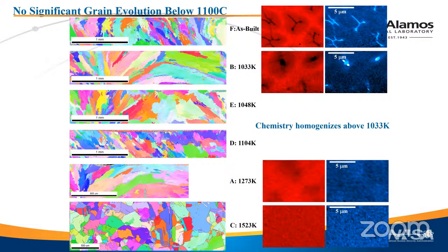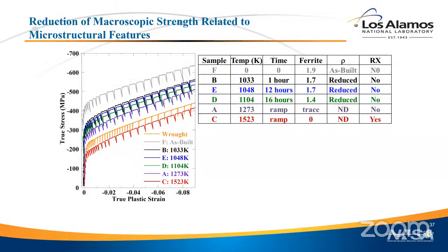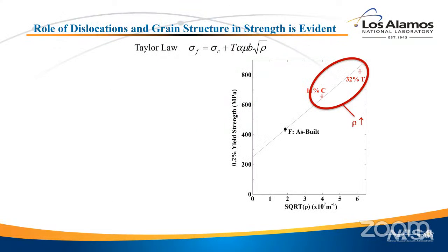So now I've shown you different temperature regimes where you can take out first dislocation density, second ferrite, third chemical segregation, and fourth grain homogeneity. And that's what this chart is trying to show, is the 6 samples that we've created by taking out one at a time the different microstructural features. And then we take those samples and deform them again and look at the strength of them. That allows us to basically assign strength to feature.